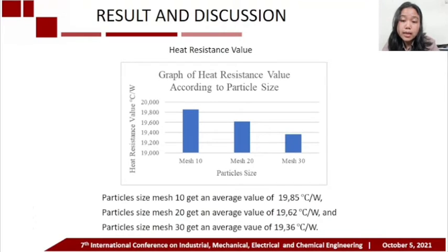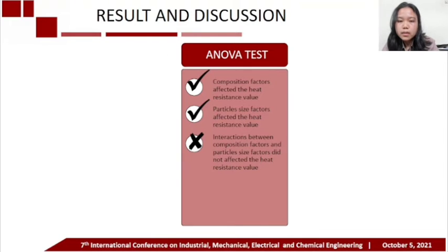Particle size mesh 10 gets an average value of 19.85 degrees Celsius per watt. Particle size mesh 20 gets an average value of 19.62 degrees Celsius per watt, and particle size mesh 30 gets an average value of 19.36 degrees Celsius per watt. The heat resistance values that have been calculated are then subjected to ANOVA testing, which is used to find out which factors affect the value of heat resistance. According to the ANOVA test, composition factors and particle size factors affected the heat resistance value, but the interaction between composition factors and particle size factors did not affect the heat resistance value.